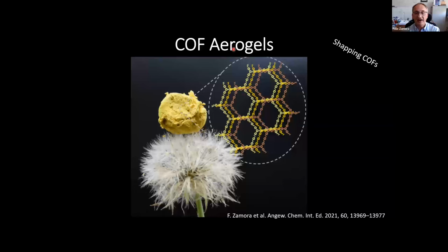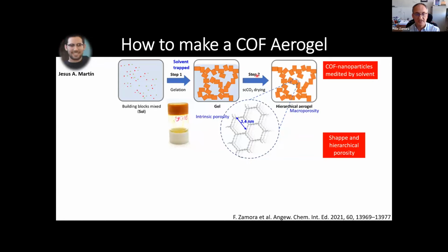Okay, so this process is based on two steps. This is the first step, in which we mix the two initial building blocks. In this case, we use a solvent instead of metacresol: we use acetic acid, with a double function, solvent and catalyst, okay? So in the first step, we form the gel. This is a picture of the gel that we form in the first step.